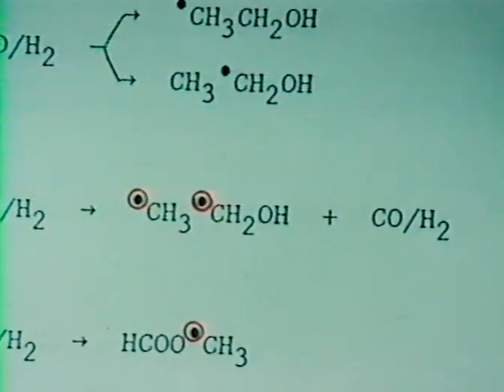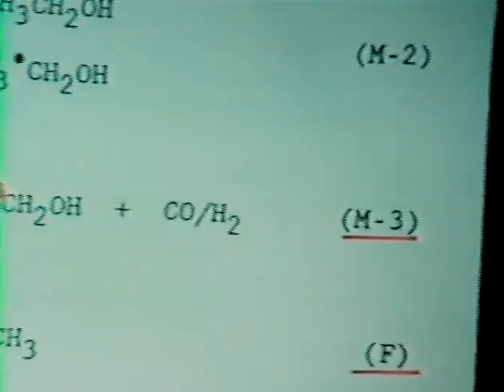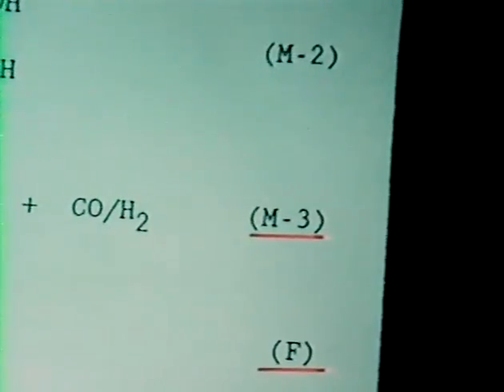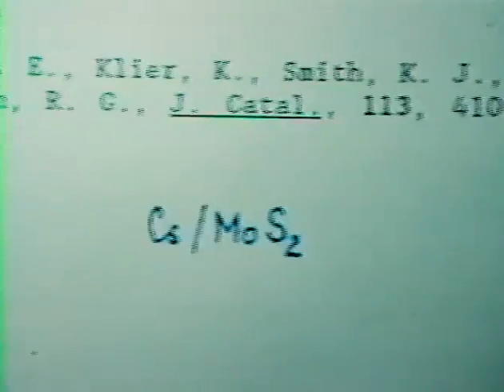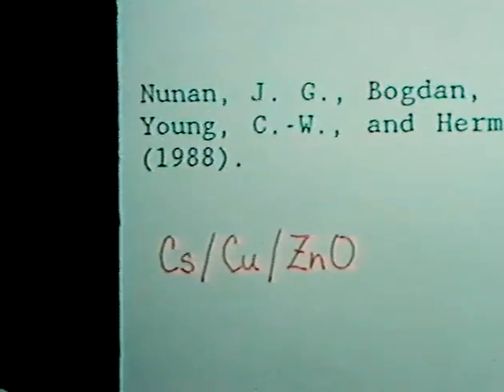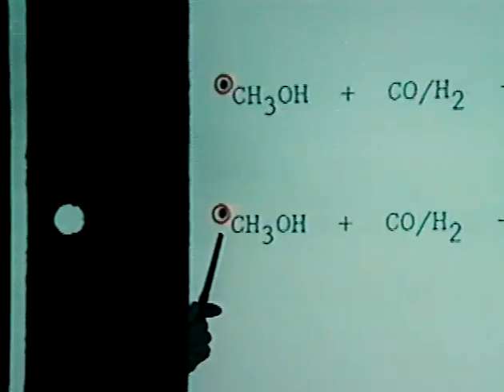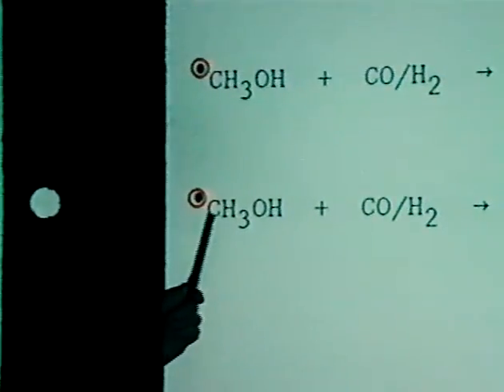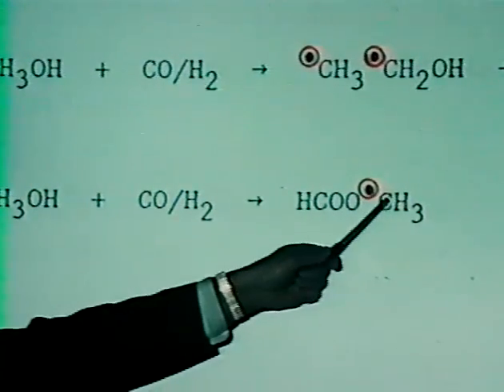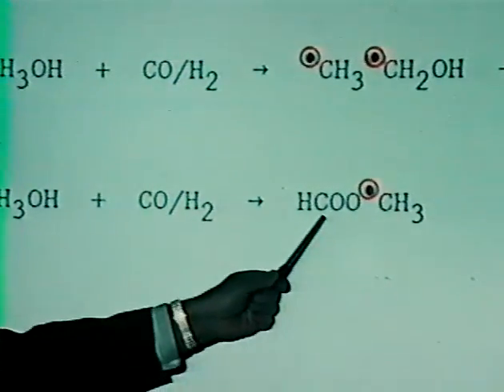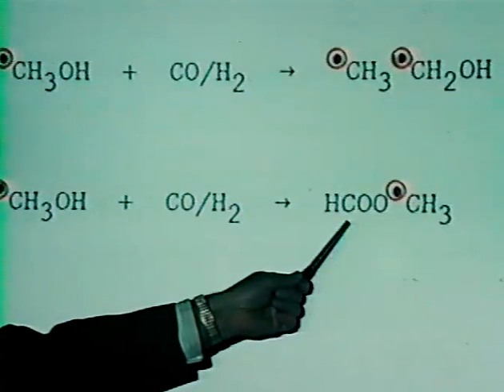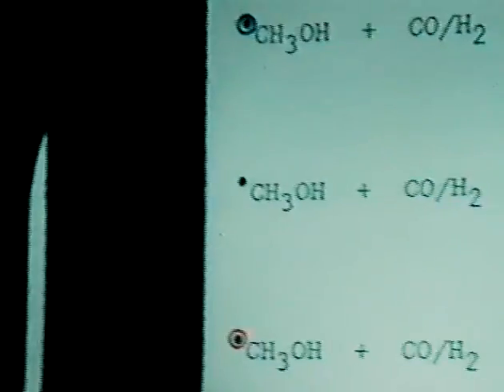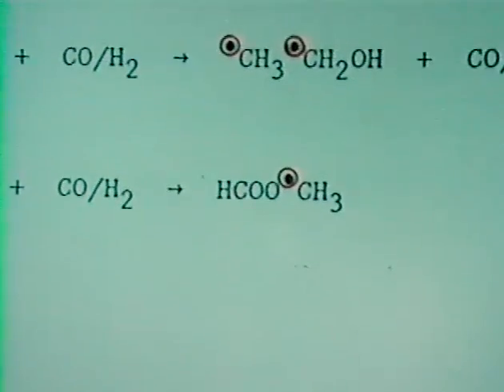This is the Lebedev mechanism. It's a beginning step of the formose chemistry, and it is in fact a very slow step. In the same system, you have another CO insertion mechanism which gives rise to methyl formate, and in that methyl formate, this carbon does come from methanol, and this carbon does come from carbon monoxide. So that also tells you that the methyl formate is not a precursor of this ethanol.